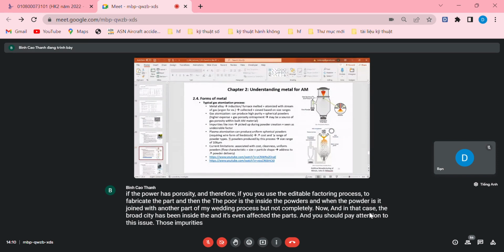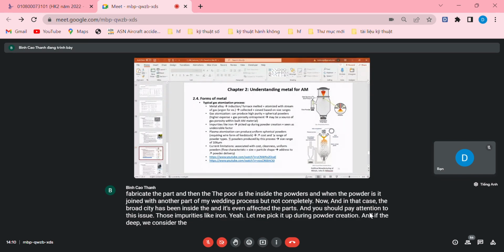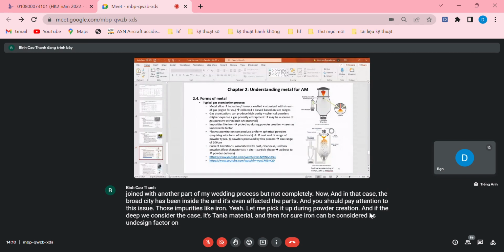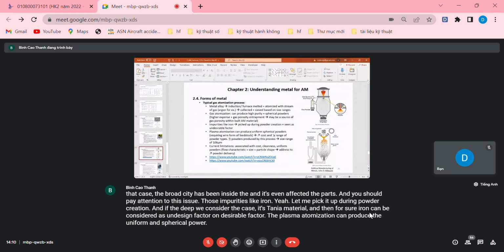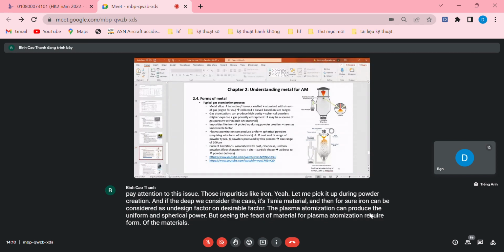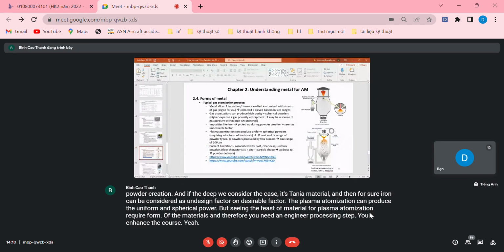Impurities like iron can be picked up during powder creation, and if we consider the case of titanium material, then for sure iron can be considered an undesirable factor. The plasma atomization can produce uniform and spherical powders. But since the feedstock material for plasma atomization requires wire form, you need an additional processing step, which increases the cost. Yeah, for sure.